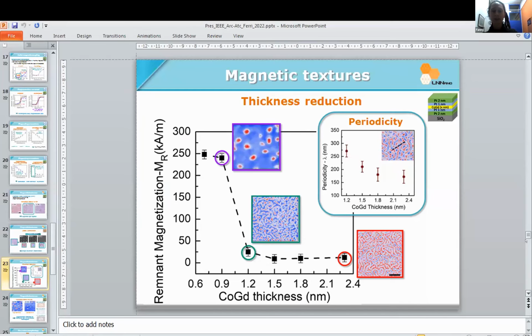And if you reduce a little more, at 0.9 nanometer, you can see a clear stabilization of individual skyrmions. So we have a really abrupt transition between a spin spiral and, between 0.9 and 1.2 nanometers, the stabilization of skyrmions. Remember that here we are at room temperature, and all this is at remanence.